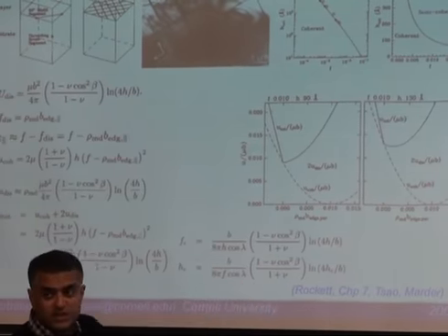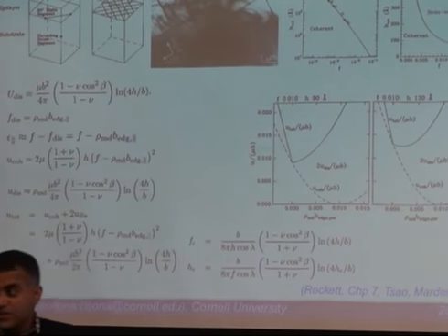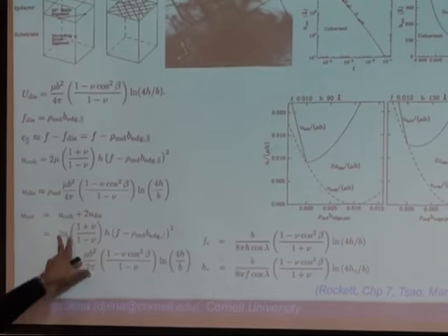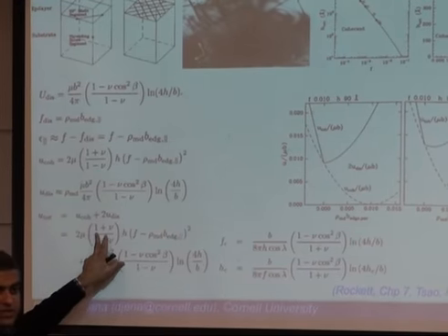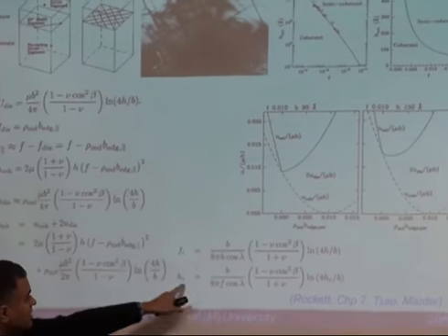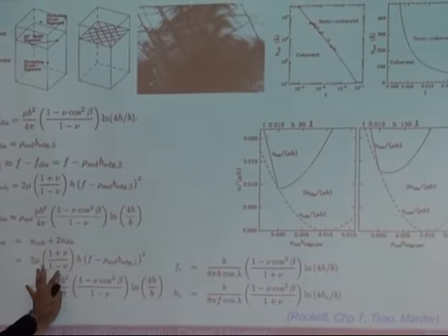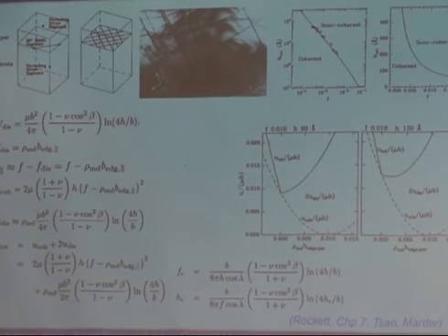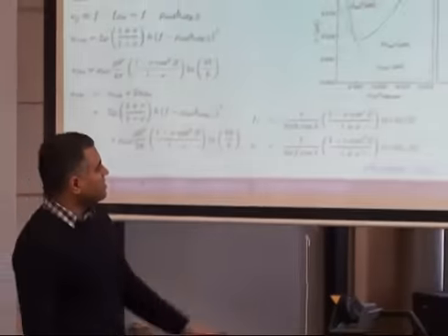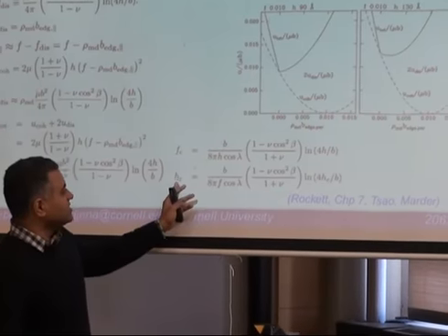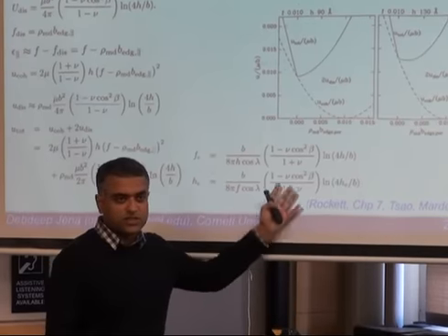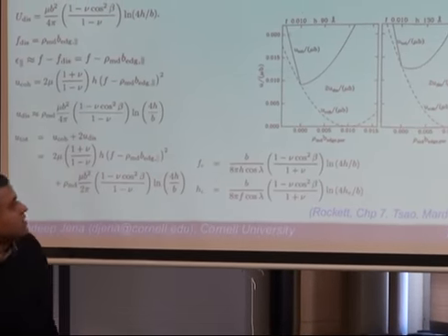Right? Is that clear? The minima shifted, so they form dislocations, and now you want to find what is that critical thickness. I think you just take a derivative of this, and equate it. If there's a minima which is not sharp, you'll pick it up, and here's the critical thickness. Essentially, it comes from this expression, right? And this is called the Matthews-Blakeslee relation, not law, but relation, and it has all these things. Basically, this is a critical thickness. Just to be careful, it also appears here, so it's not a simple formula. You have to solve it. It's a transcendental equation. You just have to solve it, and you can plot it.